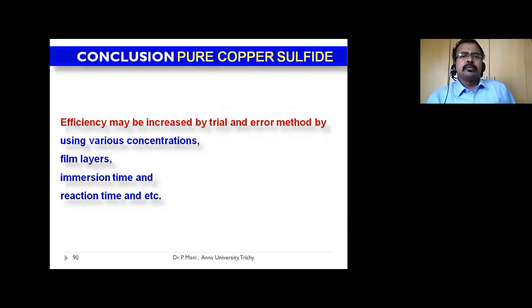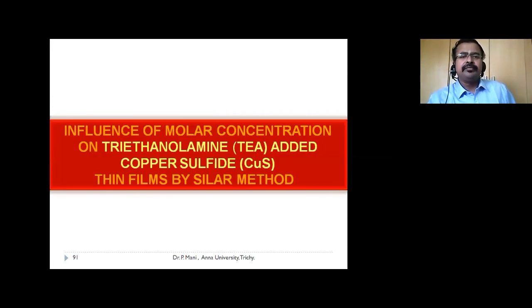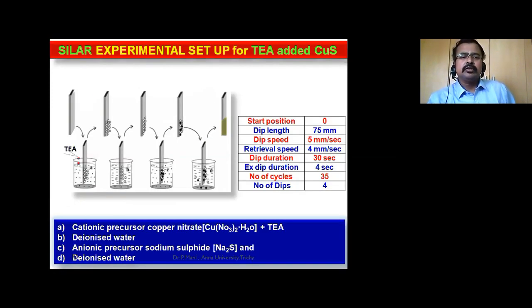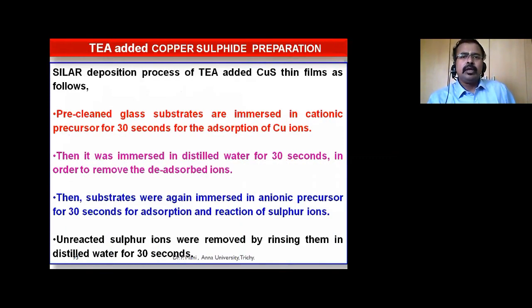Here, as a conclusion for the pure copper sulfide thin films, efficiency may be increased by trial and error method using various concentrations, film layers, immersion time, reaction time, etc. Then, TEA added copper sulfide thin films by the SILAR method, the usual setup. Pre-cleaned glass substrates are immersed in cationic precursor for 30 seconds for the adsorption of copper ions. Then it was immersed in distilled water for 30 seconds in order to remove the desorbed ions. Substrates were again immersed in anionic precursor for 30 seconds for adsorption and reaction of sulfur ions. Unreacted sulfur ions were removed by rinsing them in distilled water for 30 seconds.